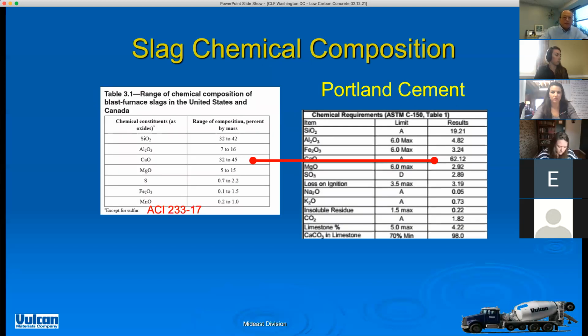Here's a little comparison to explain why slag, as a secondary cementitious material, is not as reactive as Portland cement. One of the chemical compounds we look at is CaO, or calcium oxide. With slag, this is coming from ACI, it ranges from about 32 to 45% depending on the source, and this particular Portland cement is around 62% calcium oxide. The more calcium oxide you have in a material, the more reactive it is. Next slide.